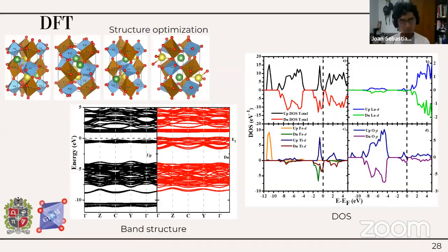And with this structure, Professor Deluque made the calculations for the bands that you can see at the bottom. In particular, in these bands, you can see that at the Fermi energy, which is denoted by the dotted line, the conduction is different for up spin and for down spin. In particular, we have a semiconductor behavior for up spin, and a metallic behavior for down spin. So we have a ferromagnetic semiconductor that could be used for spin valves, or to construct gadgets alike in the spintronic industry.